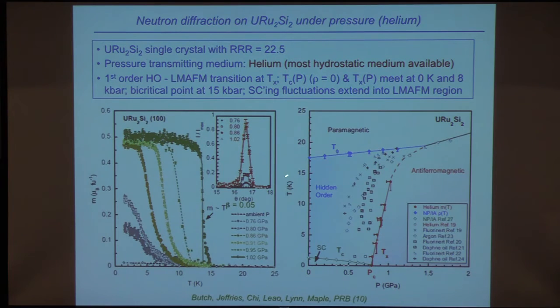And then you can deduce this temperature versus pressure phase diagram. And so here you see that the hidden order transition follows this line, and then there's a kink when you go into the antiferromagnetic phase. And then this is a line of first order transitions right here. The superconductivity lies in this region right here, and so it looks like it coexists with the hidden order, but does not coexist with the antiferromagnetic order. Okay, so again, you see a quantum phase transition right here, and you see a magnetic phase, and then a phase whose order parameter you don't even know, and then superconductivity occurring in this region right here.